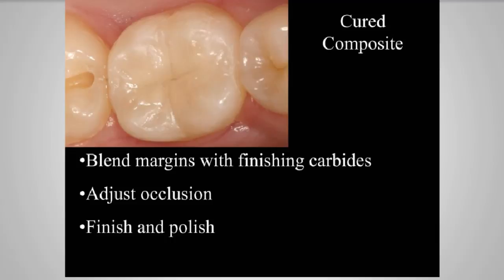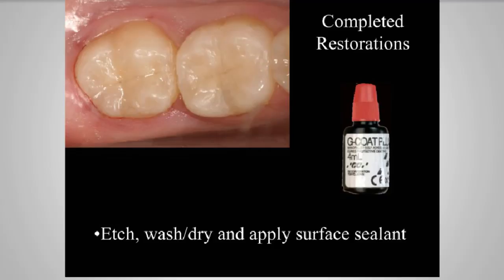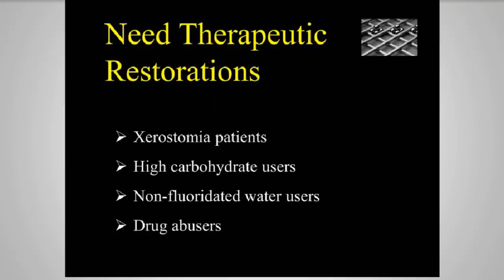I like to try to put as much anatomy as I can before I light cure. Once it's set, then I like to blend my margins using my finishing carbides, like a 7406 fine finishing carbide. I like to adjust the occlusion and then finish and polish, and then we put our surface sealant. When we do that, we acid etch it, wash it, and dry it very well, and then we place it over the two teeth. I feel very comfortable that this young 16-year-old patient is not going to have postoperative sensitivity and is going to have these restorations last for a long period of time.